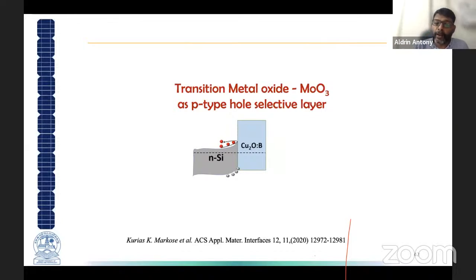But MoO3 is actually an N-type material, so how does it behave as a hole selective layer? Because MoO3 has a very high work function, and when it comes in contact with the silicon, the band bends in the upward direction. So it blocks all the electrons here, and it allows the holes to move in this direction.